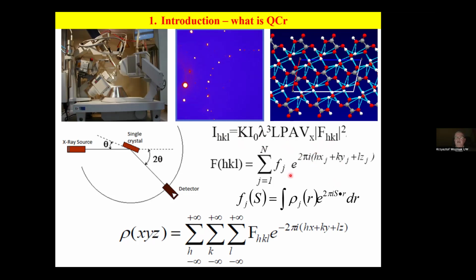Structure factors are sums of atomic contributions called atomic scattering factors, Fj, multiplied by this exponential term containing phases. Once we know phases from structure solution, we can calculate electron density maps and put atoms in the maxima of such Fourier series, thus obtaining a single crystal X-ray structure of a studied compound.